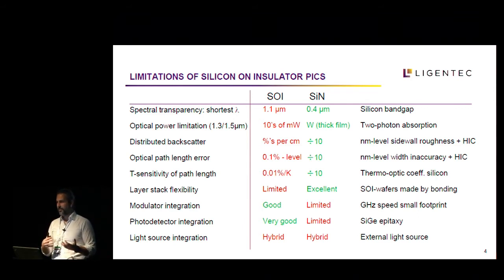But silicon is more mature. It has modulators available, taking advantage of the different plasma phenomena that can go to gigahertz speeds, and they have a rather compact footprint. There is a ready photodetector integration that is done with typical silicon germanium, which again is very efficient, it goes very fast, and it is ready today. Silicon nitride has some answers to these problems, but still in the research phase. Where both of them have a limitation is that there is no efficient light source integratable into these platforms today. And this is where a lot of hybrid integration and hybrid technology comes into place.